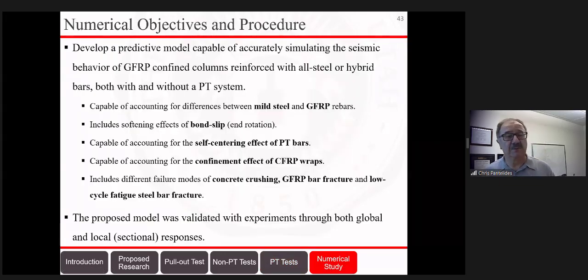So now let's go into the numerical procedure. So here, what we want to do is develop a predictive model that's capable of simulating what we saw here in these columns that we tested. We want to account for the difference between mild steel and fiberglass bars. We want to include the bond slip. We want to show the self-centering, of course, because that affects the residual displacement. And there are some impediments here. We want to make sure we are capturing the confinement of the carbon fiber wraps in the case of the post-tensioning.